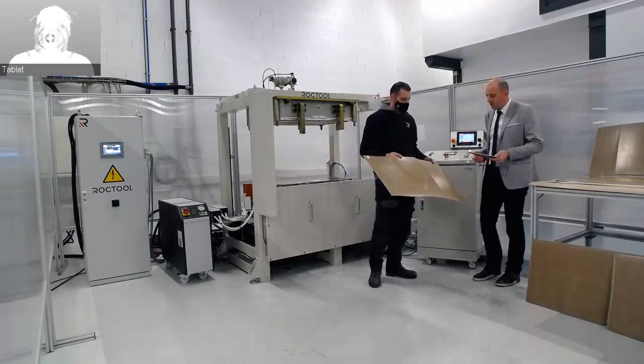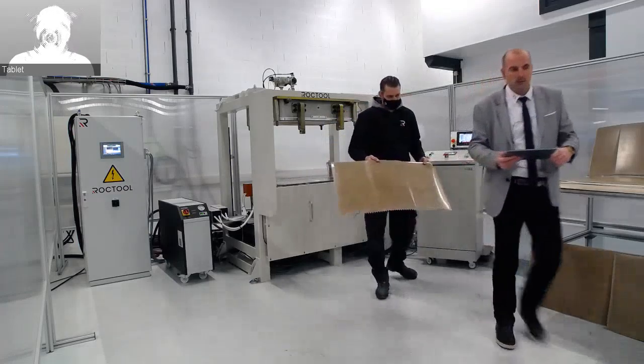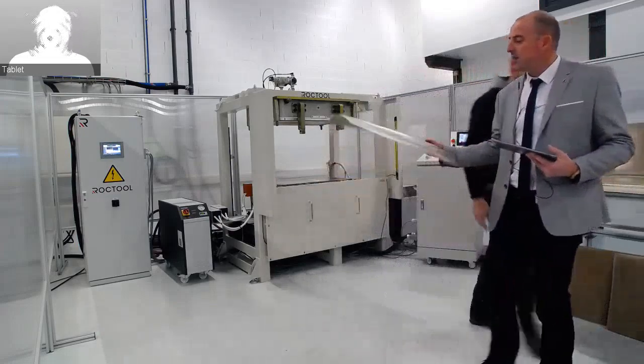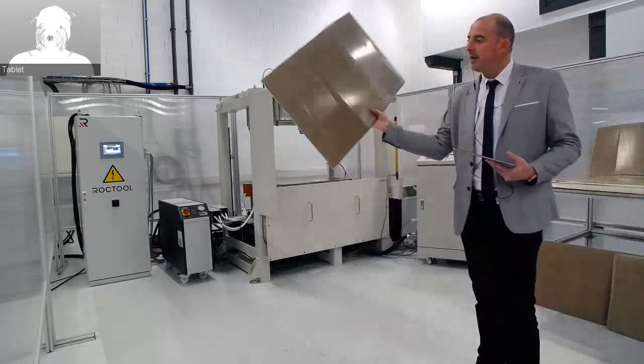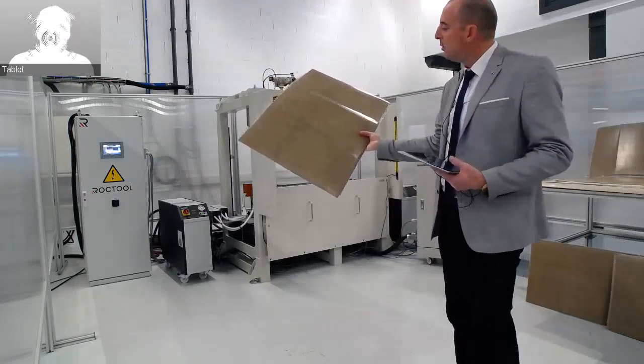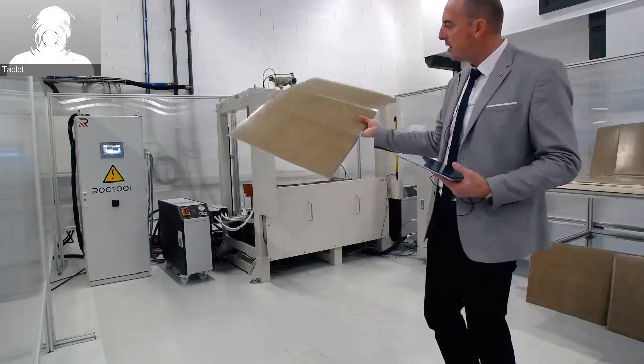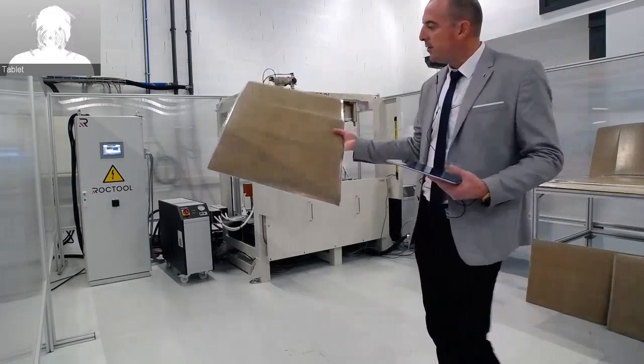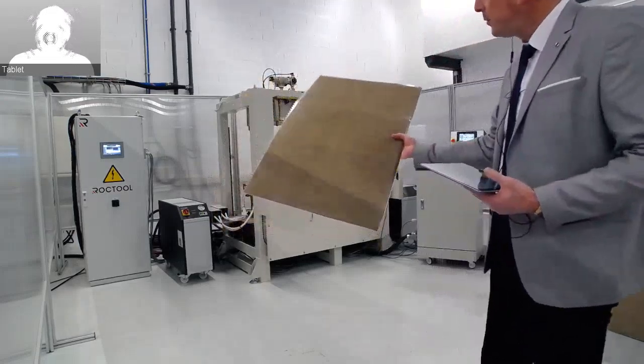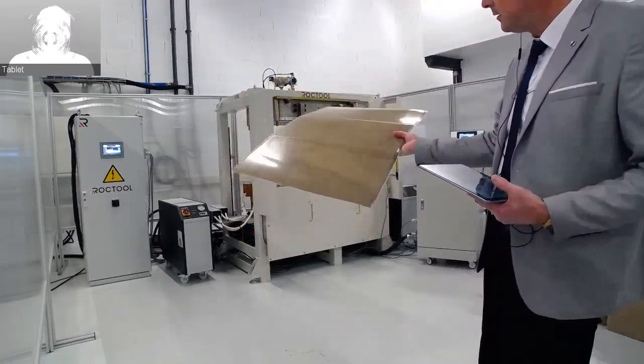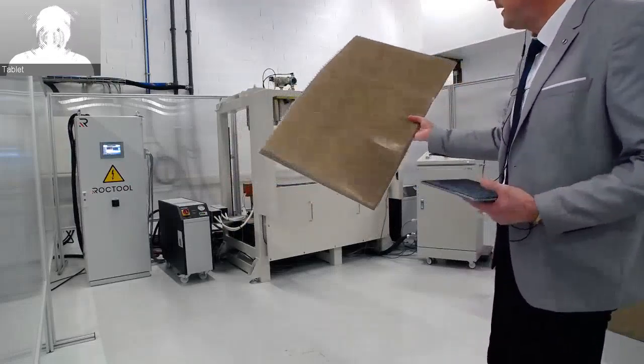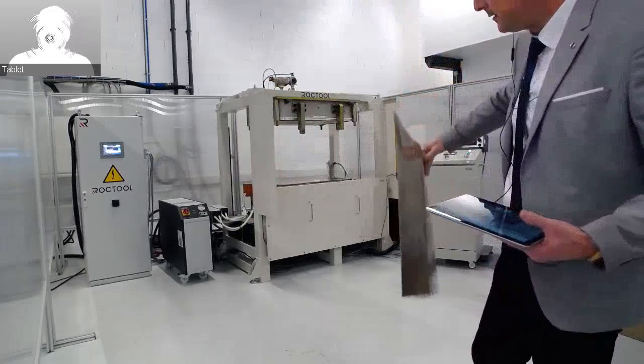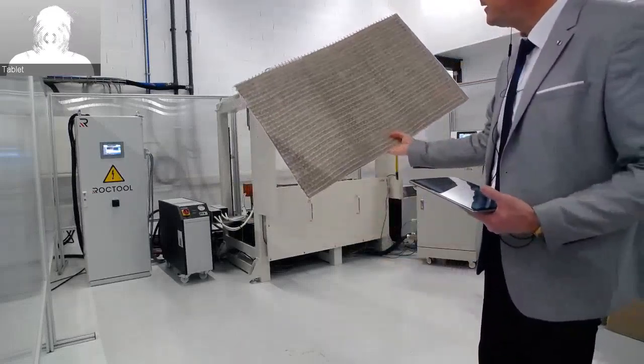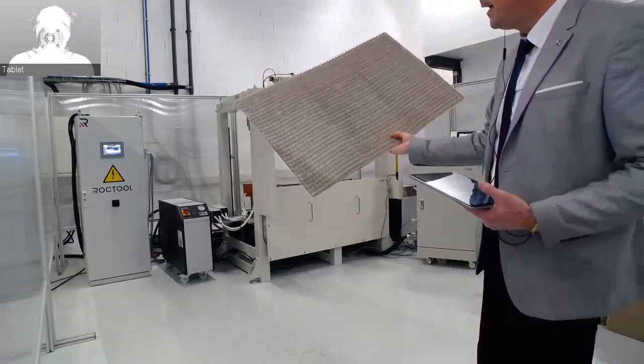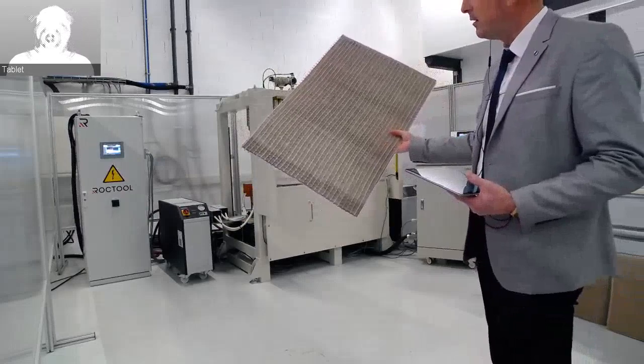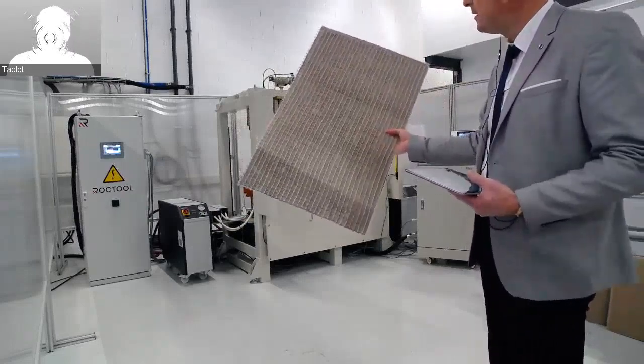So Guillaume, here you see that we have a good consolidation of parts. You see here on the tool surface, we have a very glossy aspect with a high surface quality. You see here that, as we use natural fibers, the aspect and the color of this material is really homogeneous. And you can see on the other side, the power reeds are integrated inside the composite. And with this possibility, we can obtain a really good rigidity of the composite part.